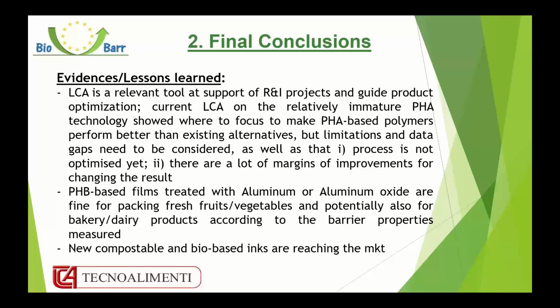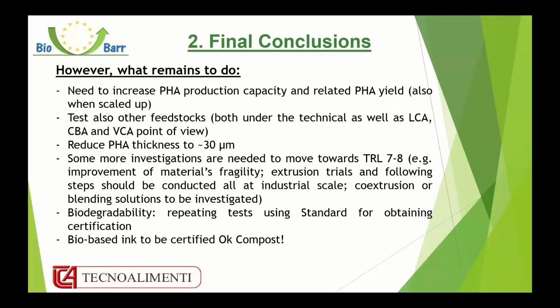PHA-based films treated with aluminum or aluminum oxide are fine for packing, for example, fresh fruits, vegetables, and potentially also bakery and dairy products, according to the barrier properties measured. New compostable and bio-based inks are reaching the market. However, there is still something which remains to do.